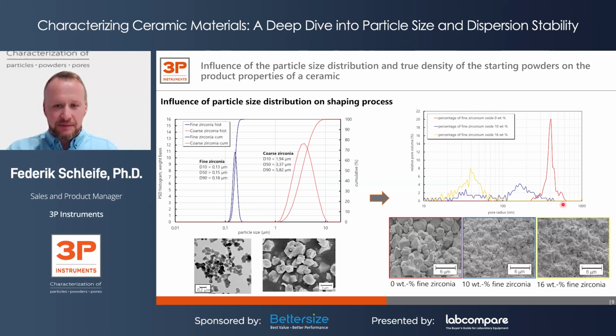When you mix the coarse powder with a bit of the fine powder, so with 10% of fine powder, and you measure again the green body density, you will see the pore radius distribution from the blue curve. Different than for the pure coarse zirconia, which gives a normal monomodal distribution of the pore sizes, the 10 weight percentage of fine zirconia and 90% of coarse zirconia powder results in a green body with a bimodal pore size distribution. So you might get some pores in a range of around 160 nanometer and some pores in a range of 35 nanometer.